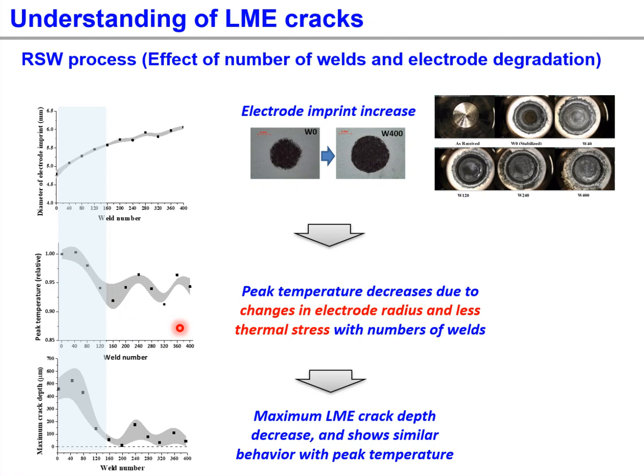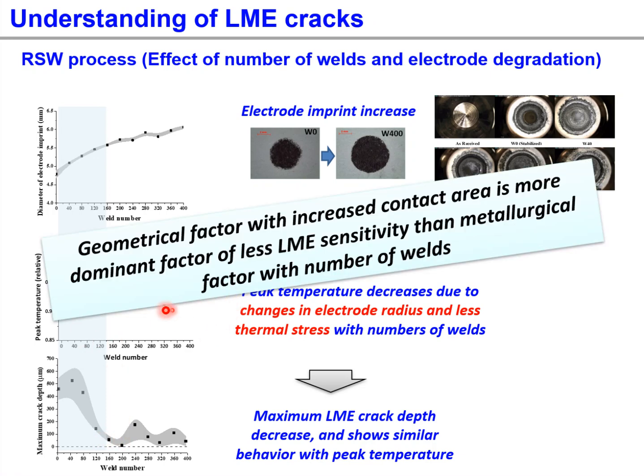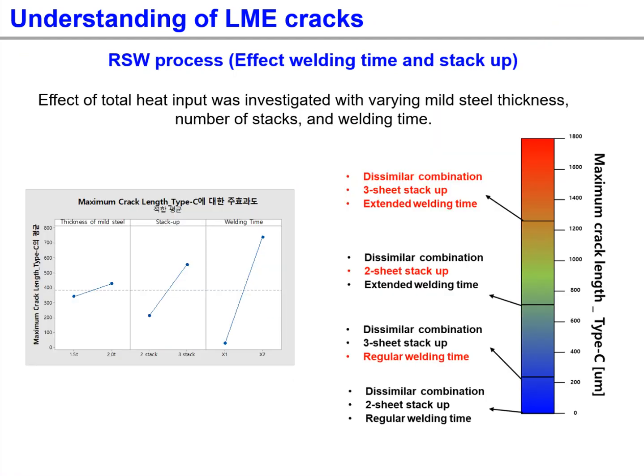due to the changes in electrode radius and less thermal stress with the number of welds. Finally, the decrease in maximum LME crack depths up to 160 welds can be well explained in conjunction with the similar behavior of the peak temperature. So the geometrical factor of increased contact area is a more dominant factor for less LME sensitivity than the metallurgical factor with number of welds.